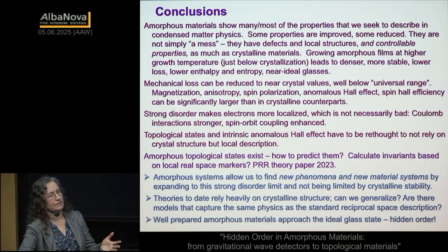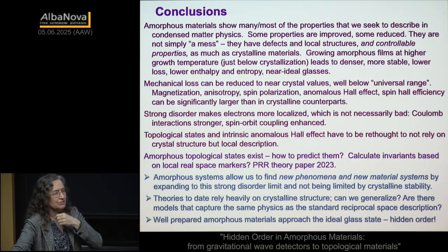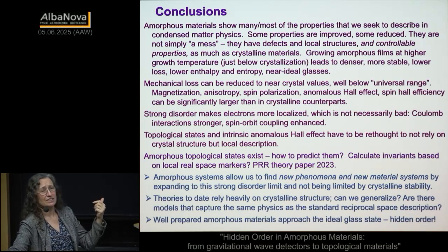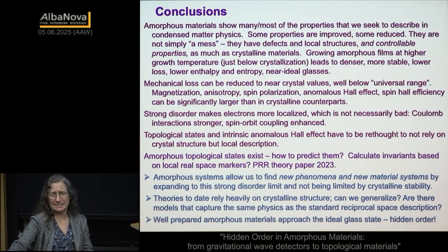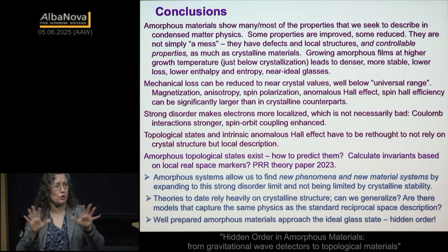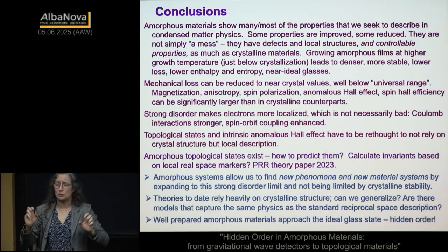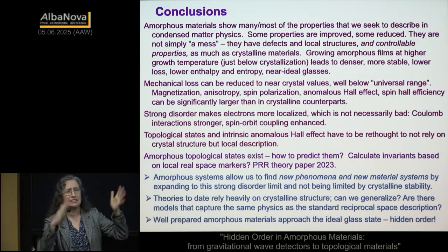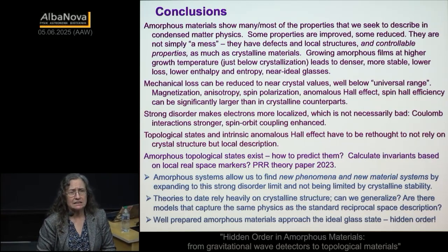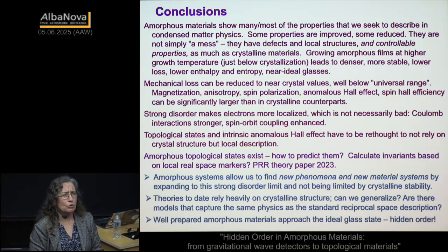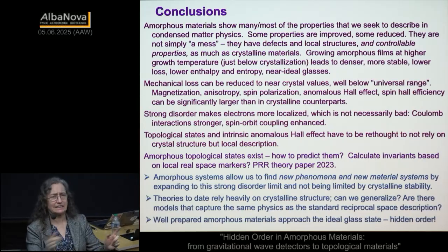But they're in totally different regimes. The dielectric loss is measured at gigahertz. The mechanical loss is measured at kilohertz. One of them is in a resonant regime, one of them is in a relaxation regime, which to those of you who know about the standard tunneling model, those words will mean something. For the rest of you, they're different. So maybe we shouldn't be surprised, but they not only don't correlate, they cross each other.